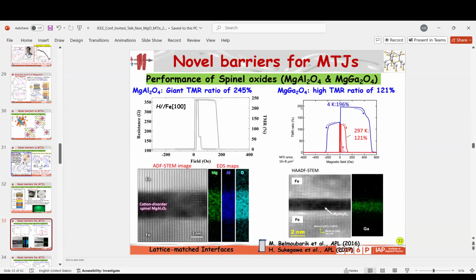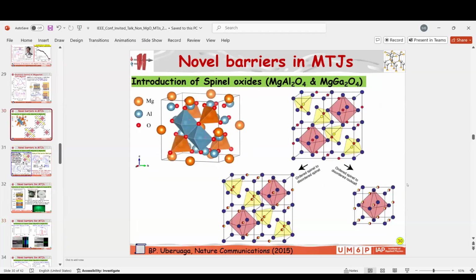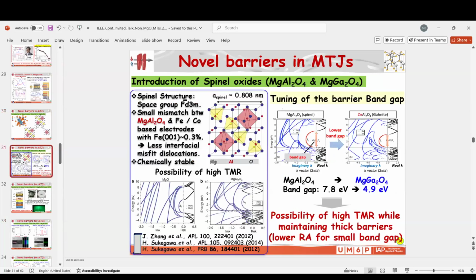Of course, the same thing happened with magnesium gallium oxide. We have a little bit lower one because of this effect, because we got an ordered one. The ordered one, in brief, will bring some band folding, which brings new bands to contribute to the conductance, which at the end lowers the MR.